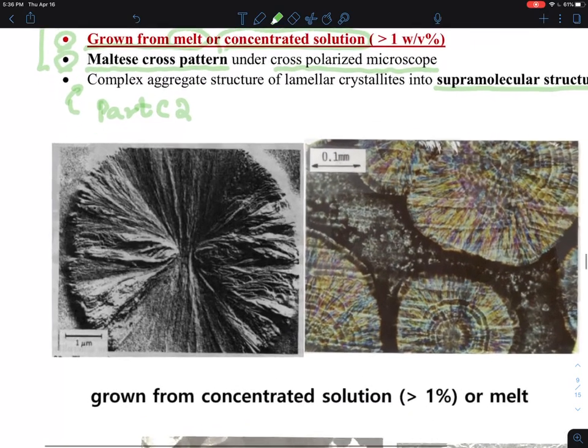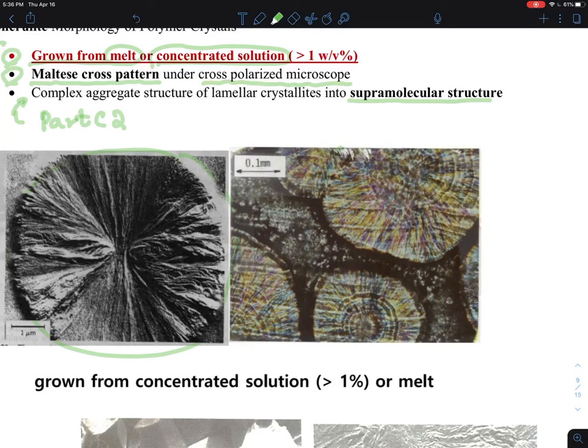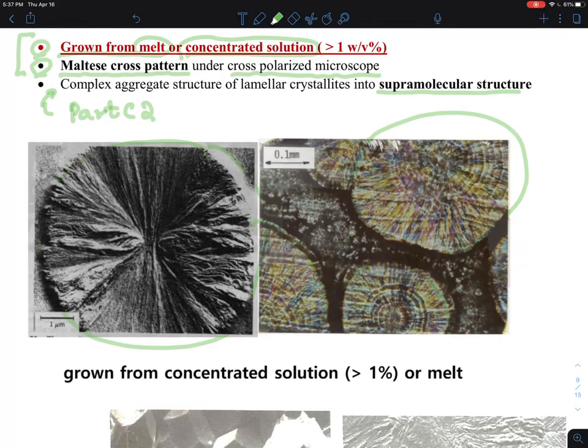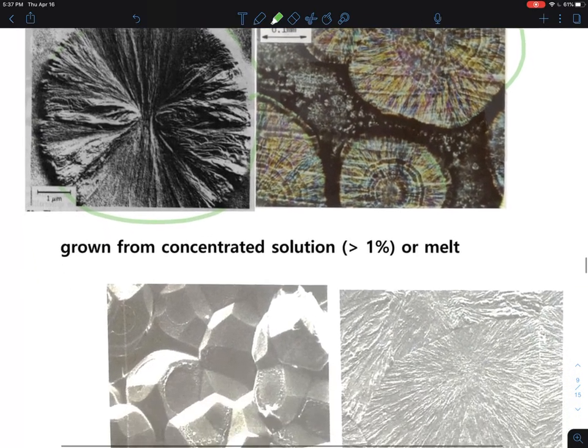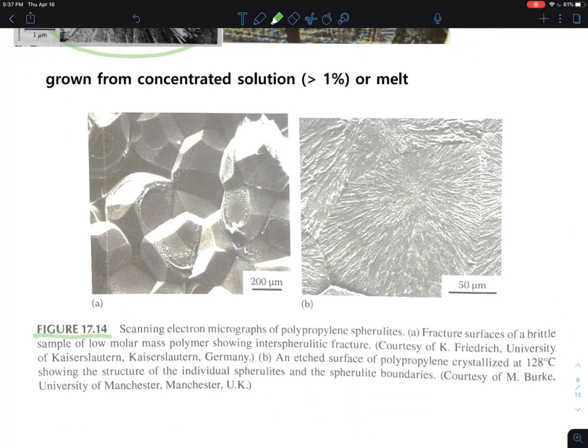This is showing one of the fractured surfaces — an SEM picture of the polymer crystal. It looks pretty large and round. This is a picture under the polarized optical microscope, and crystal domains are showing multiple colors because light sources produce rainbow colors, creating interference color patterns. This scale here is 100 micrometers, so the polymer crystal size can be really large. This picture is from textbook figure 17.14.